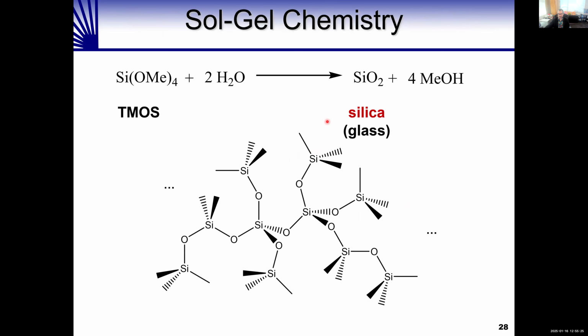There's a way to make silica, which is the glass we make our windows out of, and it's also sand. There's a way to make silica from a simple molecule called tetramethoxysilane. If you take tetramethoxysilane and put it into water, it will undergo hydrolysis and condensation to give silica, SiO2. Silica is a three-dimensional network of tetrahedral silicon atoms bridged by oxygens. When you do this at room temperature, the silica you get is amorphous, it doesn't have crystalline order.